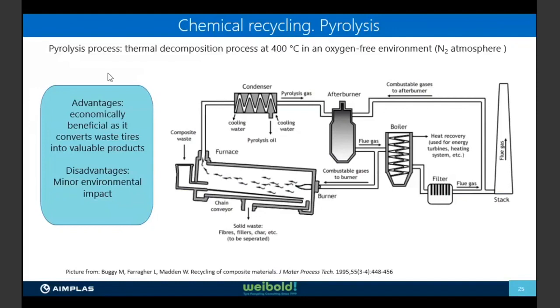And you can see here, you put the tires here, and then you reach the temperature, you get the solid waste over here, and in this way you get the gas that goes to the condenser, you get the pyrolysis oil here, and then you go this way for the pyrolysis gas. Here you have a recirculation, this is a filter, and the gas that comes over here goes again to the burner, to the pyrolysis.